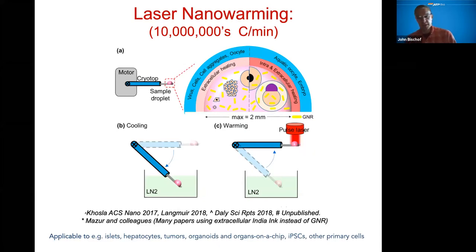In our lab, we've taken some of the concepts from Peter, and we've been trying to scale it and create a platform technology. Where Peter was able to work on a mouse oocyte or a mouse embryo in the 100 micron size range, we were trying to work on something like a zebrafish embryo, which is an aquatic species. Nobody's been able to work on that. It's a very important genetic and biomedical model system. Pretty much everybody's heard of it. The issue is that they're about 1,000 times larger in volume than a mouse oocyte. They're almost a millimeter across, and there's no way to just heat it from the outside alone to have a successful preservation. Peter Mazur tried this with India ink and it just did not work.